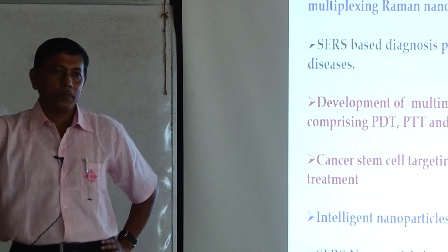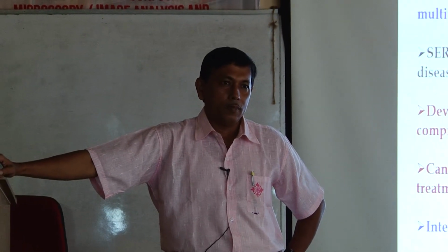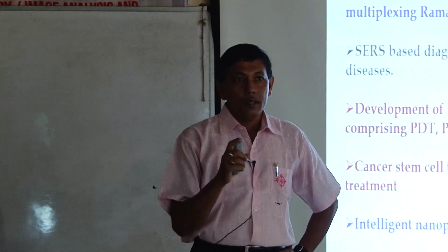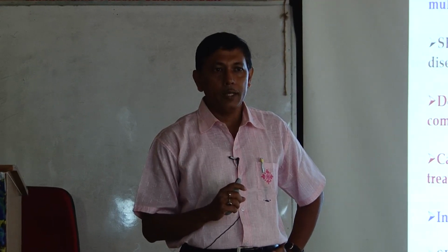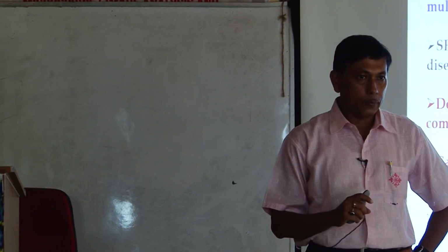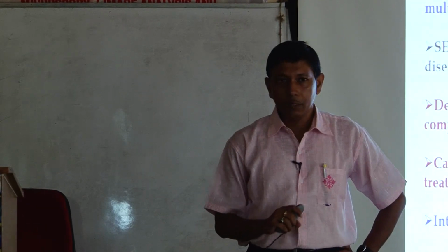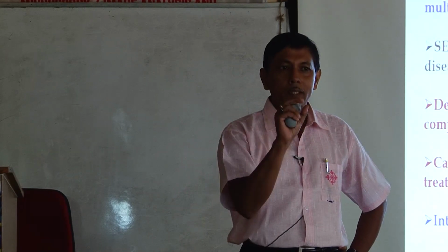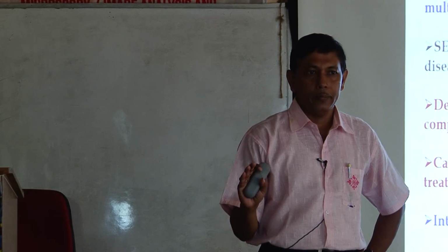When these particles come in cluster size, gold nanocluster, copper nanocluster, will it be Raman active? Yeah. Raman activity, if you use it as a substrate, definitely depends on its size and shape, mostly size. It has been found that in the case of gold, if it is a cluster, maybe 2 nanometer or 3 nanometer size, it may not be Raman active.